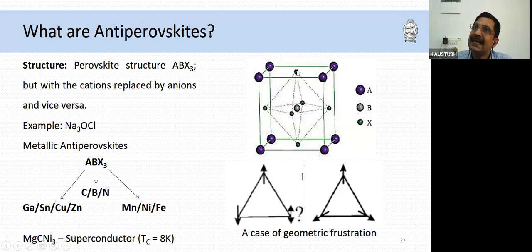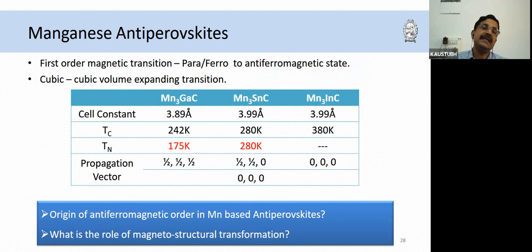And we know that in a triangular lattice, we cannot have long-range antiferromagnetic order because it always leads to frustration. So therefore, we thought, how are these materials classified as antiferromagnets? Because literature showed that, for example, if I take Mn3GaC, it had an antiferromagnetic ground state with a TN of about 175 Kelvin, and neutron diffraction identified the propagation vector to be one half. If I take Mn3SnC, it also had an antiferromagnetic ground state with a TN of 280 Kelvin, and I will talk about this. This is from our own work, where we identified both the orders, and it has an antiferromagnetic propagation vector along one half, one half, 0.